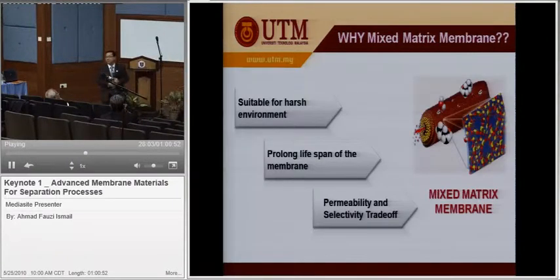And why do we develop this? This is because it is suitable for harsh environments. Polymer cannot be used for temperatures more than 60 degrees C, even though the Tg is about 180 or 200. But to get it done better, it must be operated below 60 degrees C. So that's why we develop mixed matrix. Another one is the lifespan of the membrane. Polymer, very short. The highest, maybe 3 years.